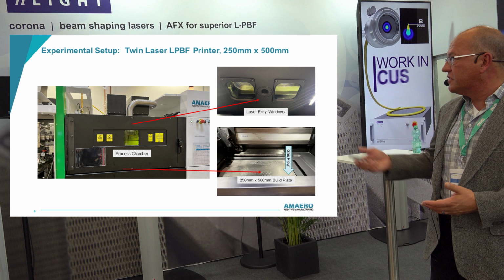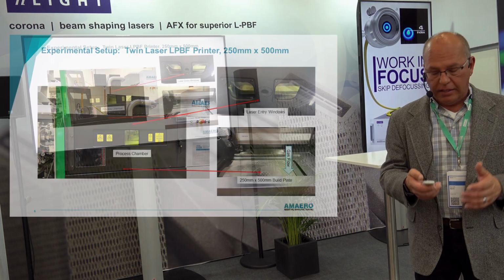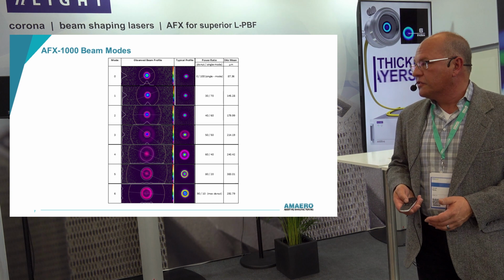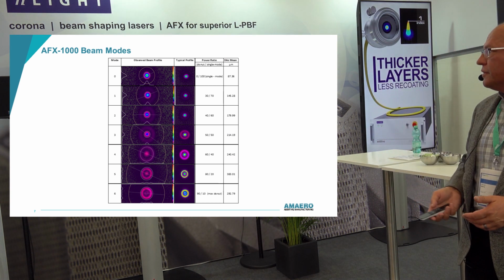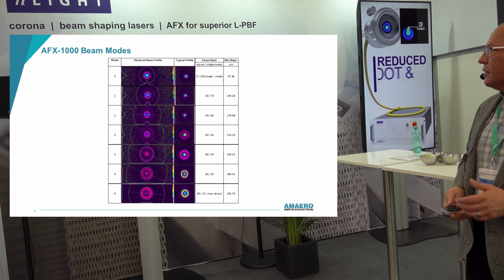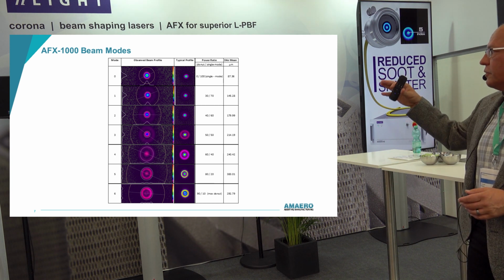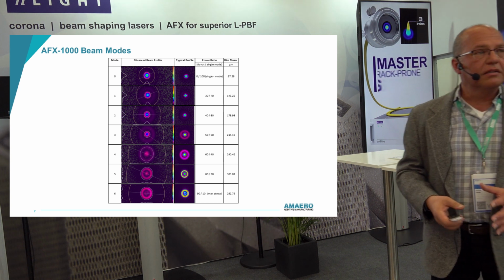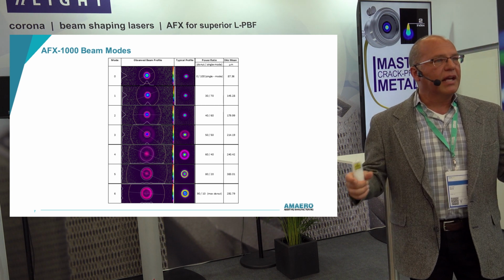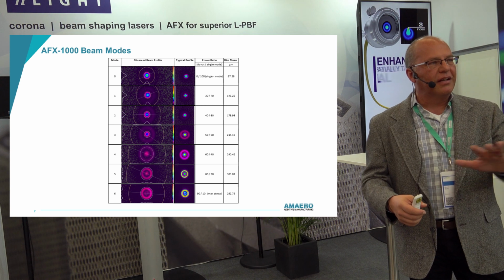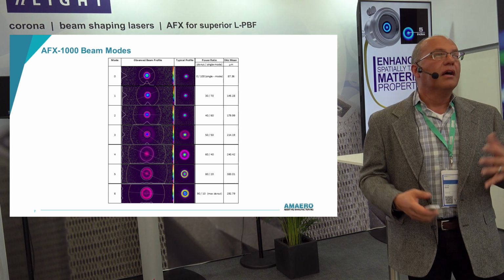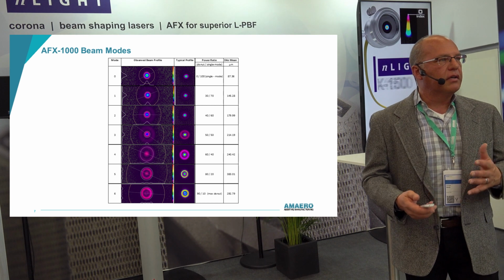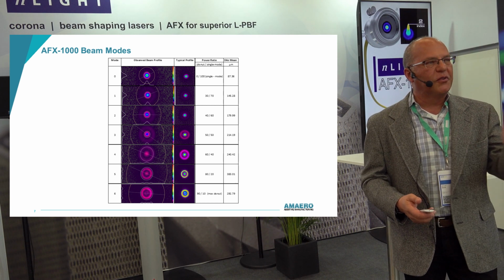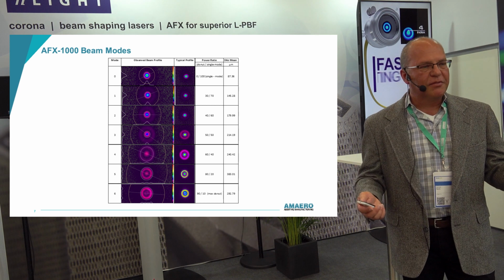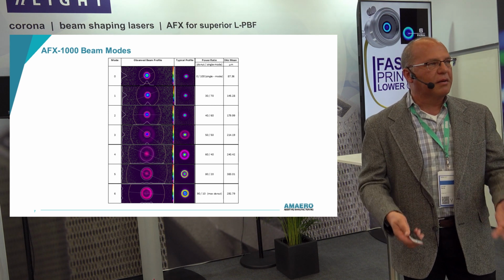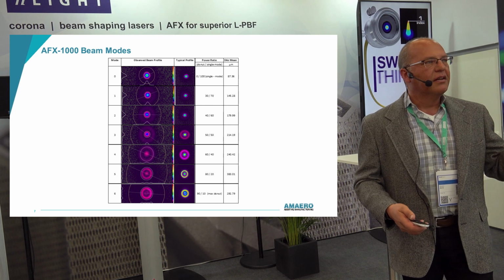And we got an opportunity to simply pull a laser out of one side of our machine and put the AFX in. So this is what happens when you put the beam profiler under it. We get in mode 0 a more traditional Gaussian spot, and as we go through modes 1 through 6, we get this really interesting ring that's hotter on the outside and a nice cool spot in the middle. And that's going to really help us avoid that whole keyhole process. Now, a smart person probably would have done a DOE, stepping from mode 0 through mode 6. I'm kind of crazy, so I went straight to mode 6 because I wanted to compare. I know how bad my life is in a Gaussian spot.